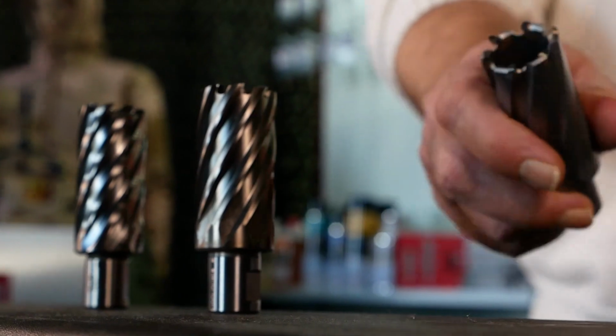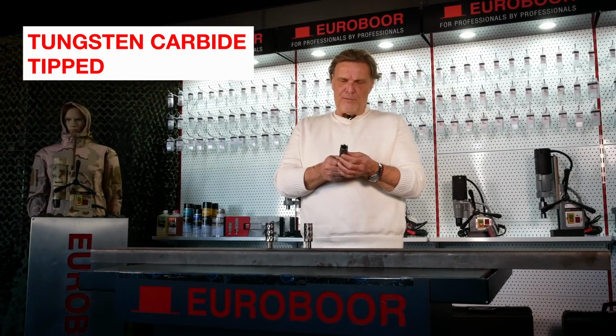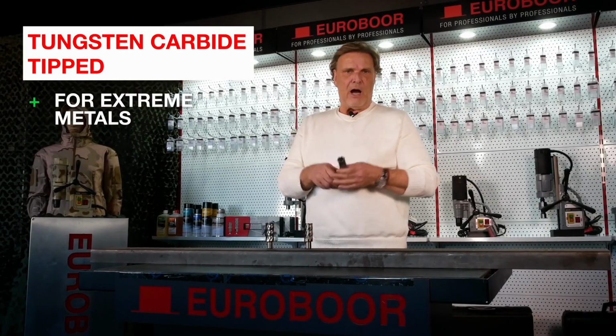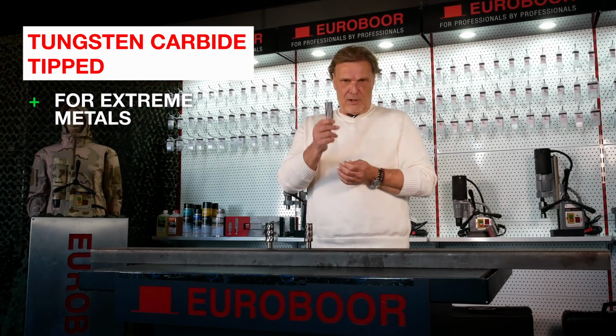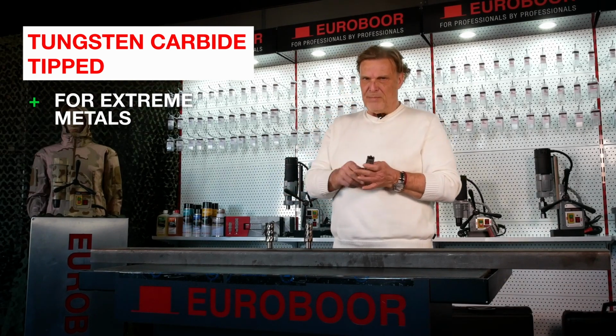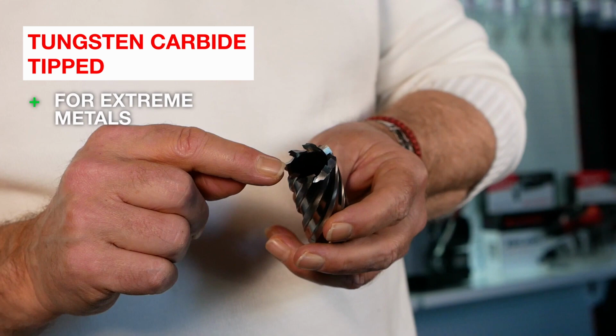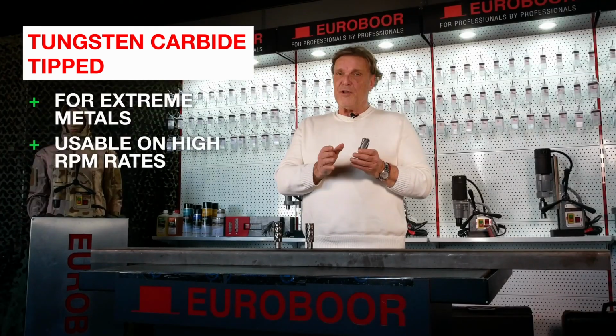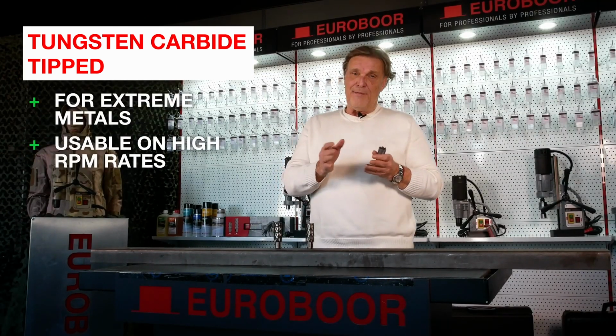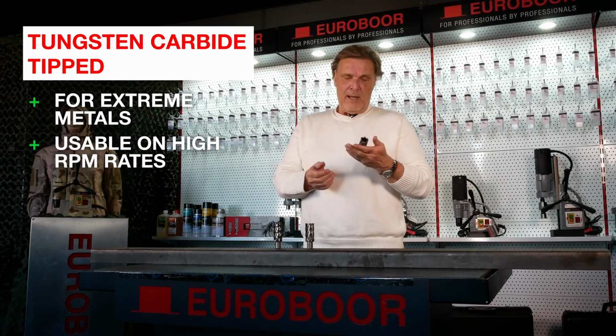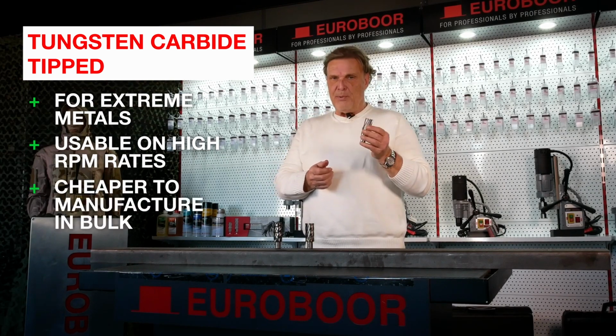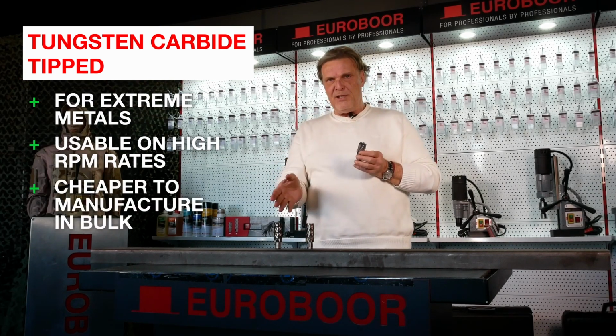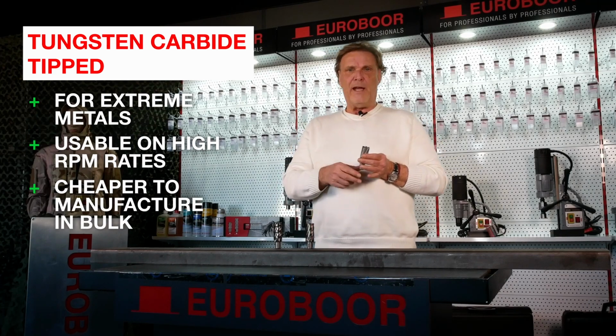On top of that, there are the TCT cutters, which you really use for extreme metals like Hardox and austenitic steels. This cutter will do the job where the other two will perform much more poorly. You can use higher RPM rates, and starting from a size of, let's say, 50 mm or 2 inches and up, TCT cutters become cheaper to manufacture than high-speed steel and the more expensive cobalt cutters.